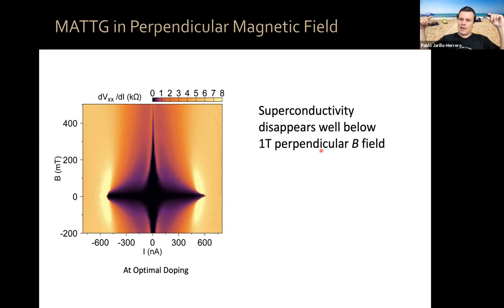if we try to apply a magnetic field parallel to the trilayer plane, and we try to induce the same type of vortices, like one flux quantum per moiré unit cell in the lateral dimension, that would take hundreds of Tesla. So this means these two-dimensional superconductors are very good for looking at the effect of effectively a Zeeman field on the superconductivity.